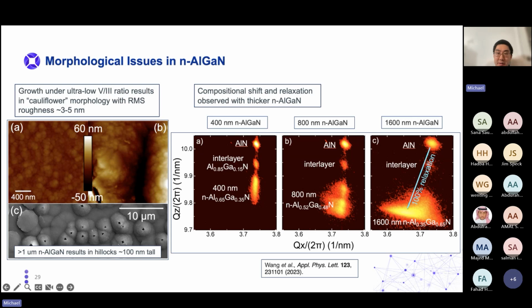All of this is the same growth condition, the exact same flow rates, the exact same temperature. And what happens is the aluminum starts decreasing in the material, and more gallium is incorporated. Additionally, the material is beginning to relax. So at the full 1600 nanometers, we can see 100% relaxation of the n-type aluminum gallium nitride, and over here it's all the way down to 35% aluminum.